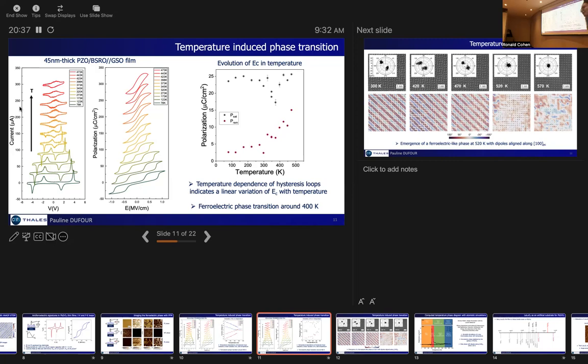Sorry, the one that you showed the microscopy. Did you switch them before? Yes, actually, we checked the electrical properties beforehand, before preparing the samples, and for the measurements in temperature, when we get back to room temperature, we could observe again the antiferroelectric phase with the antipolar displacement. So we didn't observe any pinning of the ferroelectric state in our samples. It's just that when you apply an electric field in addition to temperature, it seems that you degrade a bit the antiferroelectric properties when you get back to room temperature. But for the STEM images, just heating the sample didn't affect the antiferroelectric properties afterwards.